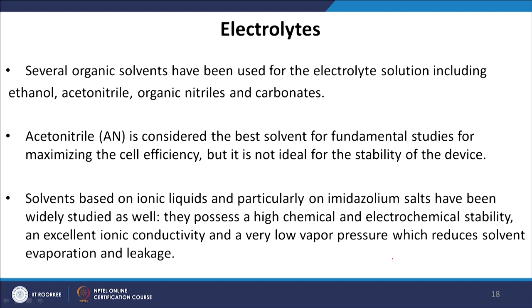Acetonitrile is considered the best solvent for fundamental studies to maximize cell efficiency, but it is not ideal for device stability. Solvents based on ionic liquids — particularly imidazolium salts — have been widely studied. They possess high chemical and electrochemical stability, excellent ionic conductivity, and very low vapor pressure, which reduces solvent evaporation and leakage. Since iodine/triiodide electrolytes are volatile and corrosive, people have explored imidazolium salts and various other ionic liquids as alternative electrolyte media.